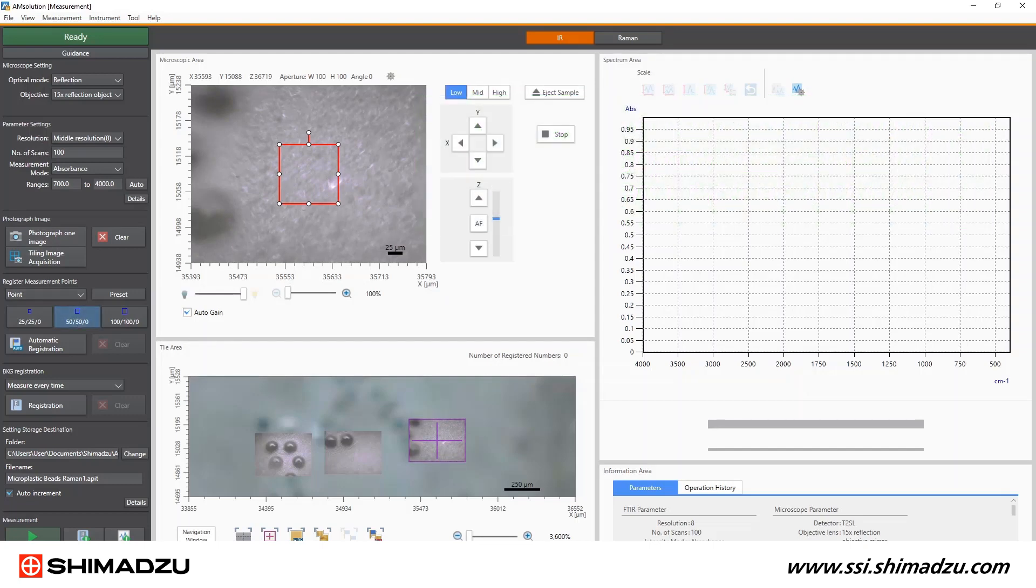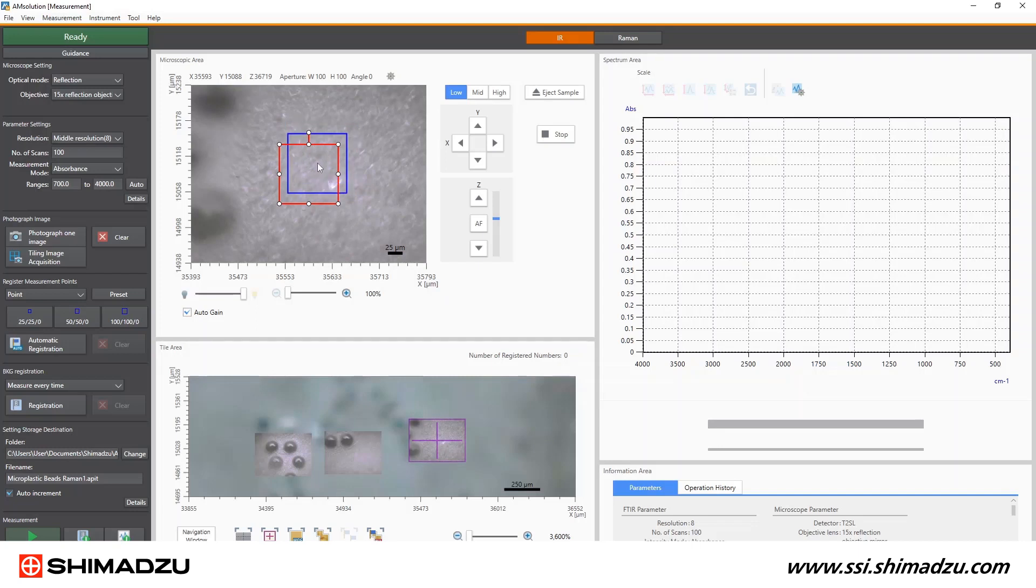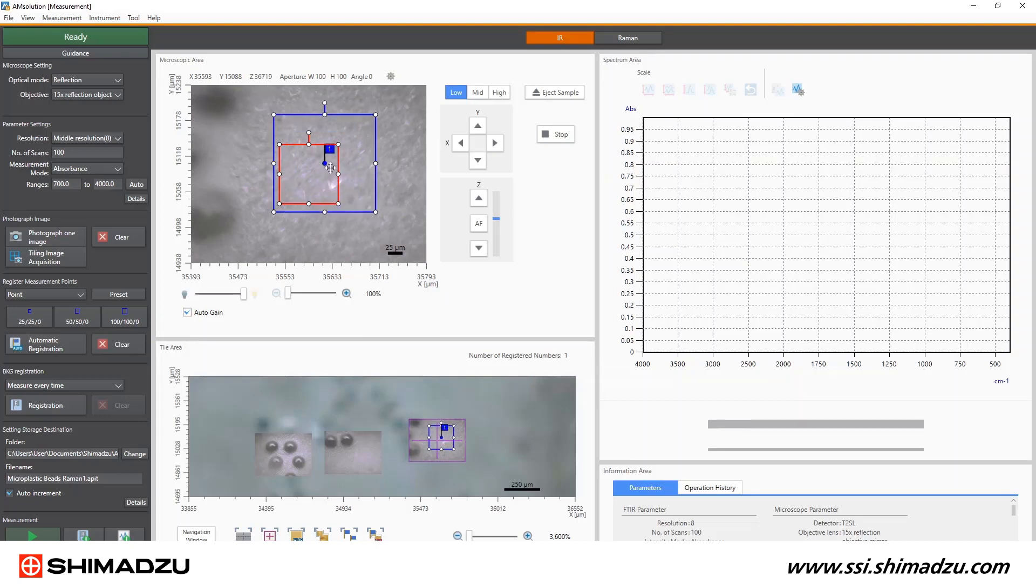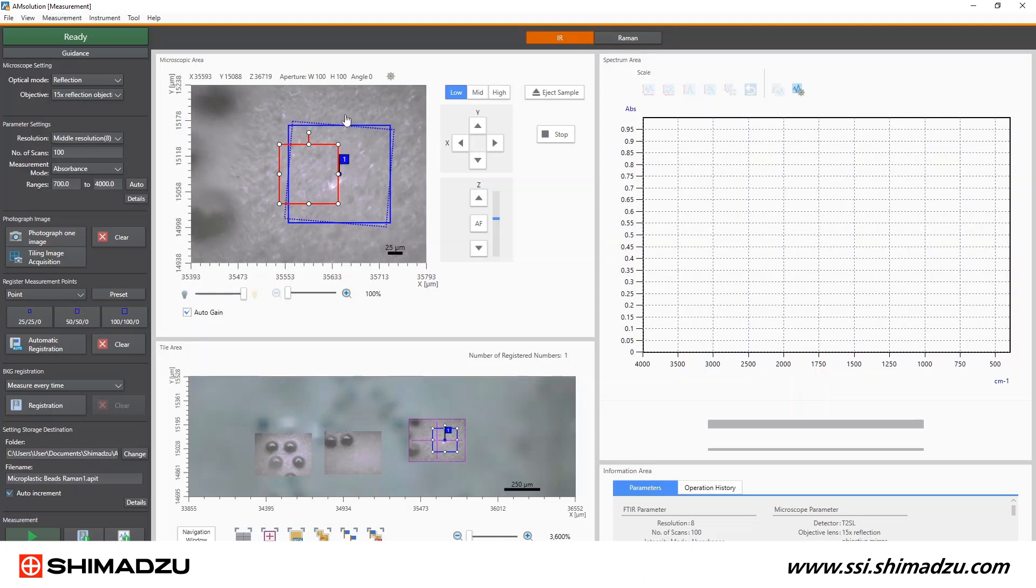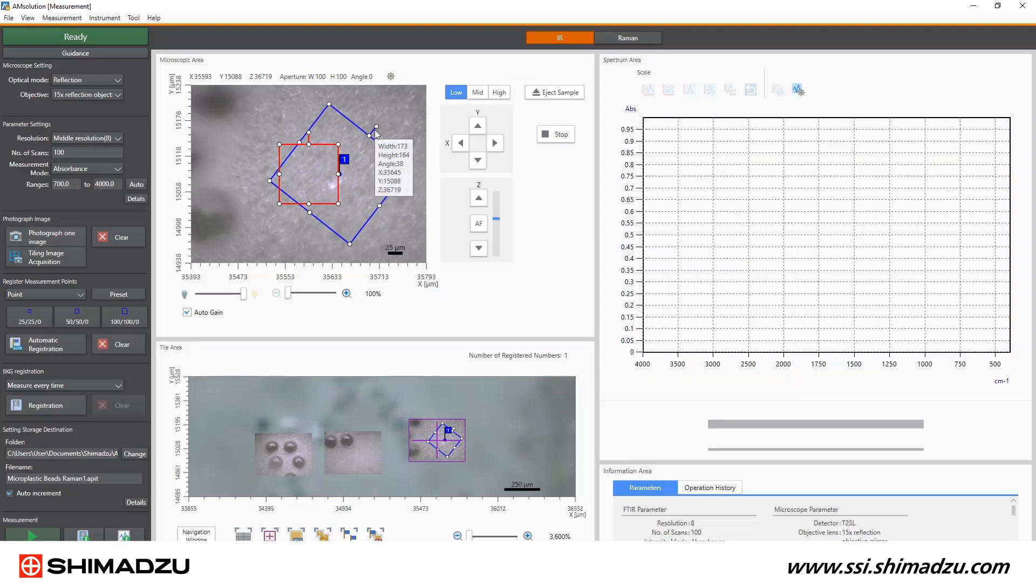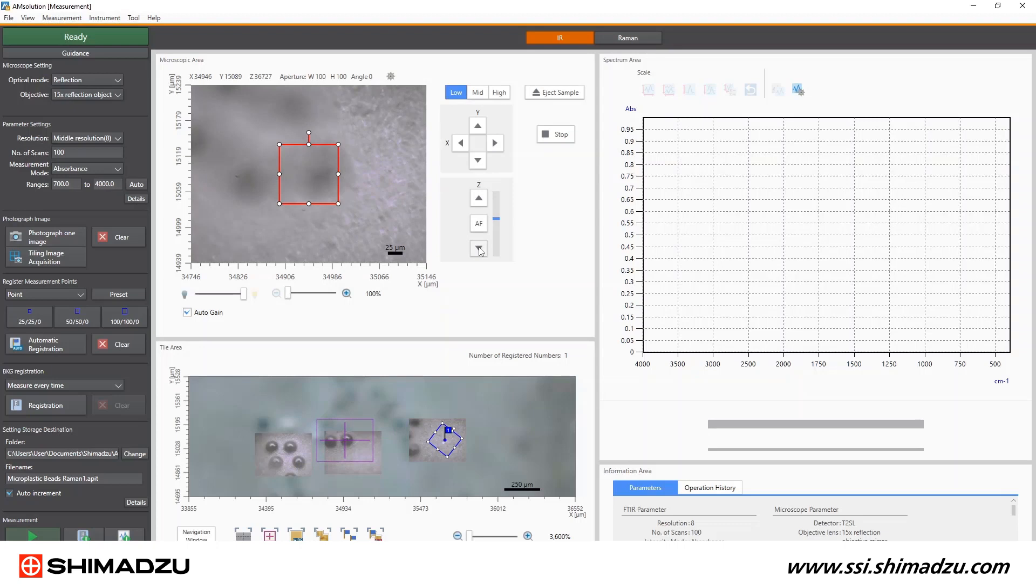Next, I need to select the aperture size. I'm going to start with 50 by 50 microns, but this can easily be adjusted later. Simply click on the spot you want to measure with the IR microscope. How about this one right here? And the blue aperture box will appear with the flag numbered 1. The aperture size doesn't quite match up with this microplastic bead, so let me adjust the boundary and orientation to capture as much of the microplastic without sampling the surrounding filter. The X, Y, Z and aperture size are all saved with this registered point. Now I'm going to repeat this location selection process for a few more interesting spots.